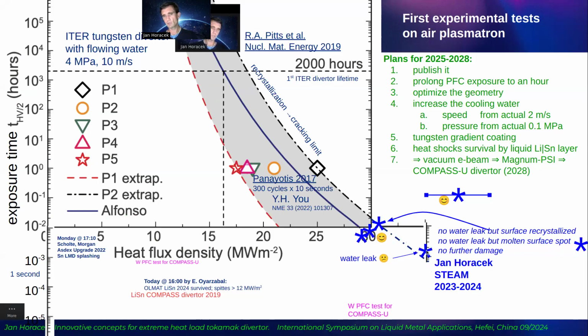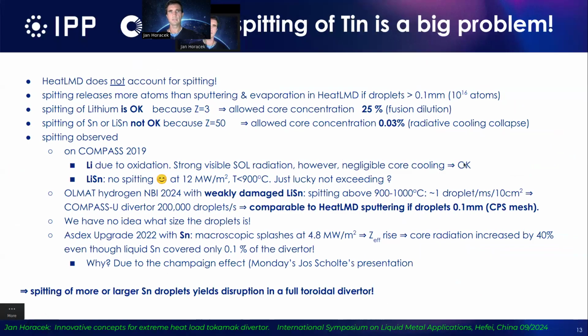We believe to get to the recrystallization limit already in spring, and now in September to much higher values than this, probably about 70 megawatt per square meter or more for 7 minutes. But this has to be still verified. What we see with the liquid metals, I would say, is quite successful, and we will continue with this.